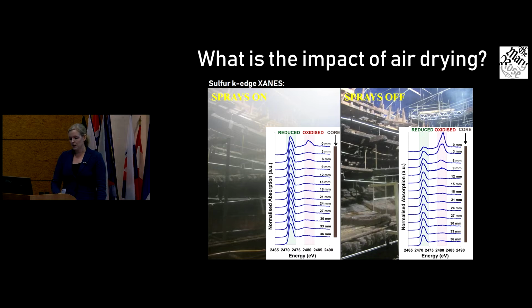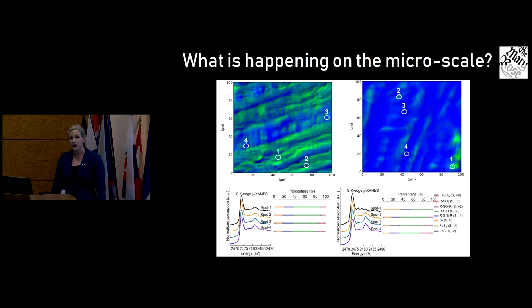We then came here to ID21 and we took those same core samples and took very thin sections of them to try and map what was there. So we had a couple of explanations yesterday about how you can XRF map at different energies to show you where the different oxidation states of sulfur are.